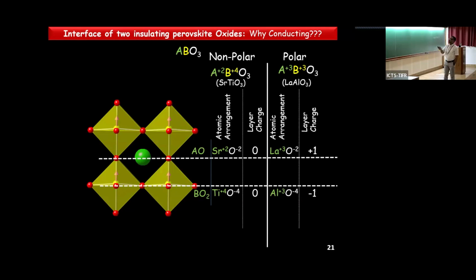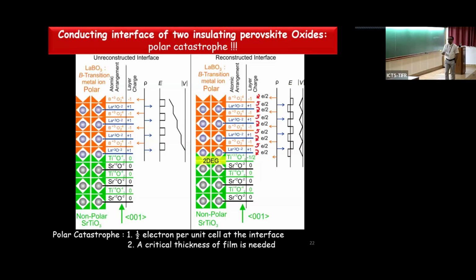On the other hand, if you think about lanthanum aluminum oxide, then this layer has a -1 charge and this layer has a +1 charge. So it is alternating plus minus, but overall it's a charge neutral material. If you take a non-polar material as a substrate and start growing polar material on top of that, then you have -1, +1, -1, +1, and this gives rise to an electric field like this. When you convert this electric field to a potential, it gives rise to a diverging potential.